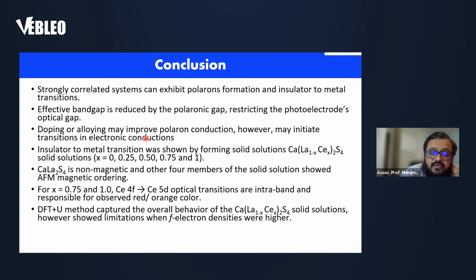Doping and alloying may improve polaron conduction by suppressing the polaron or adding some delocalized hybridization with the polaron states. However, they may initiate some kind of electronic transition, such as insulator to metal transition. We have shown in this presentation that when you form a solid solution by adding cerium to calcium lanthanum sulfide, from x equals 0 to x equals 1, the transition goes from a Mott or charge transfer type Mott insulator to almost metal-type behavior, or a metal-type electronic signature, in calcium cerium sulfide.